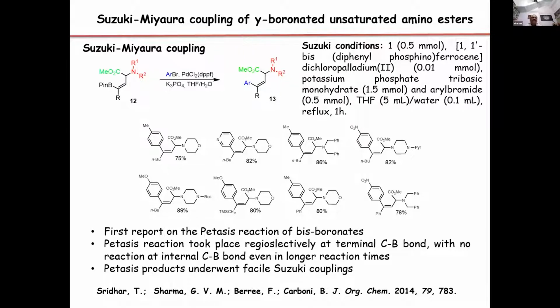Then these amino esters are subjected to the Suzuki reaction, making use of gamma boronated systems, in the presence of palladium as a catalyst to get the Petasis-Suzuki products exclusively with very good yields. And this is the first report on Petasis reaction making use of bisboronates. Similarly, the Petasis reaction has occurred only at the terminal C-boron bond, leaving the internal C-boron bond untouched, and Petasis products underwent facile Suzuki couplings to give the amino acid systems.